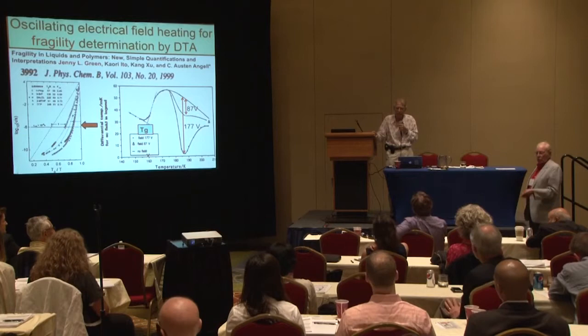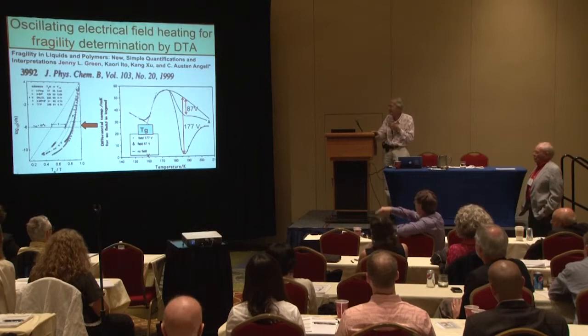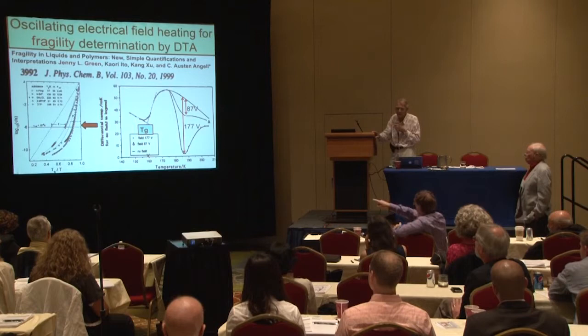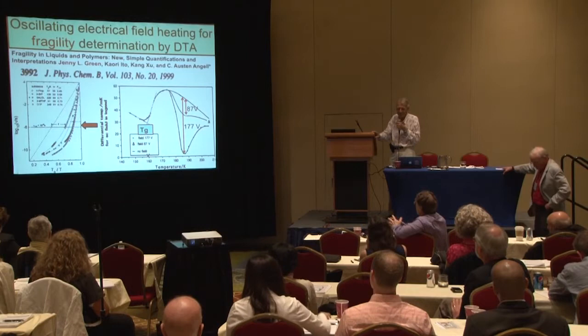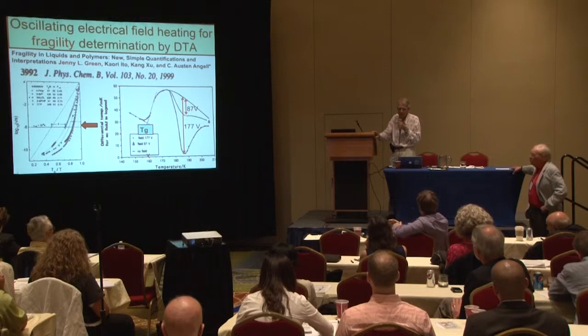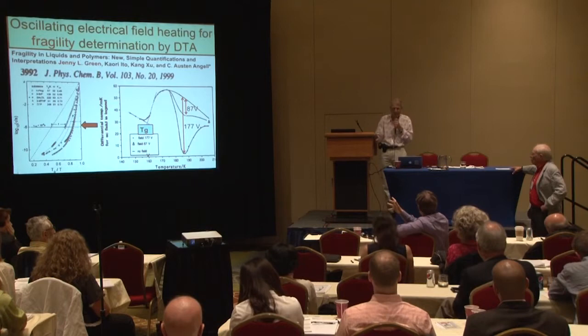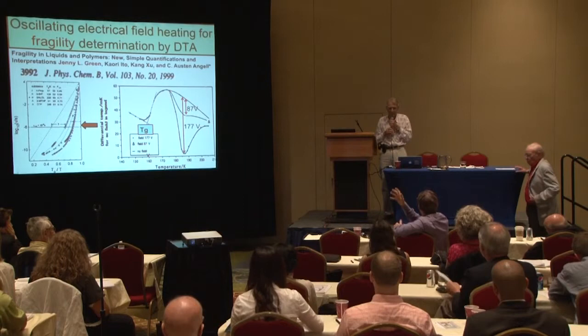This is not really an essential question, but it's going to be on this slide right here. If you're using the absorption of electromagnetic energy to quantify the fragility of the solution, it brings up a more general question. Why do you call solutions with that kind of slope fragile and solutions with a more linear slope strong? There must be some implication about the way the systems are bonded together. And it seems important to us because cryoprotectant solutions, in cryobiology, they all tend to be fragile glass formers. I don't know what the physical implication of that is versus a strong glass former.